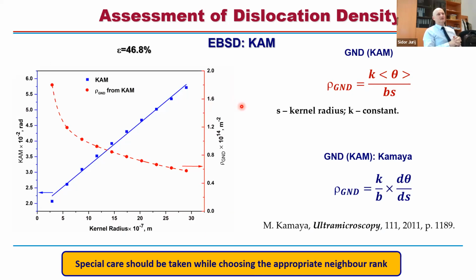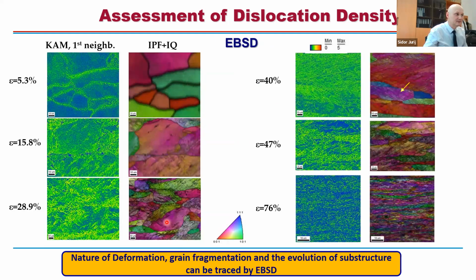Then another thing: when you calculate the kernel average misorientation, there is a way to calculate the amount of geometrically necessary dislocations. So you have two types of dislocations: geometrically necessary dislocations and statistically stored dislocations, like immobile ones, which are statistically stored. And GNDs, basically, are produced by the gradients which are observed inside particular grains, right?